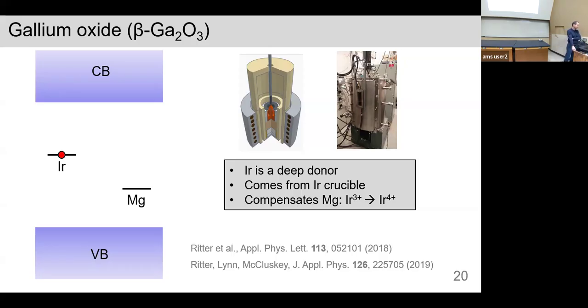So we discovered that it's a deep donor, so it can donate an electron. And if we dope the crystal with magnesium, which is an acceptor, then the magnesium will be compensated by the iridium. And what that does is it just donates its electron to this acceptor. So that results in the so-called iridium 4+ oxidation state. And then magnesium is negatively charged.